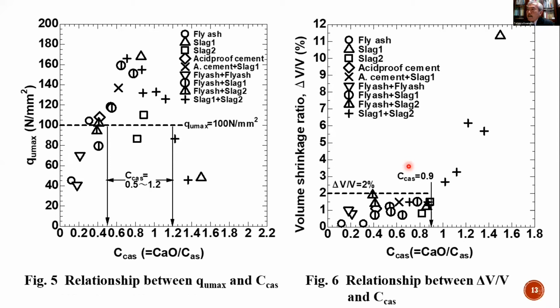Using the factor Ccas, some mechanical properties can be characterized well. For example, in figure 5, Qmax greater than or equal to 100 Newton per square millimeter can be obtained when Ccas is in the region of 0.5 to 1.2. And in figure 6, the volume shrinkage ratio, delta V over V, becomes less than 2% when Ccas is smaller than 0.9.